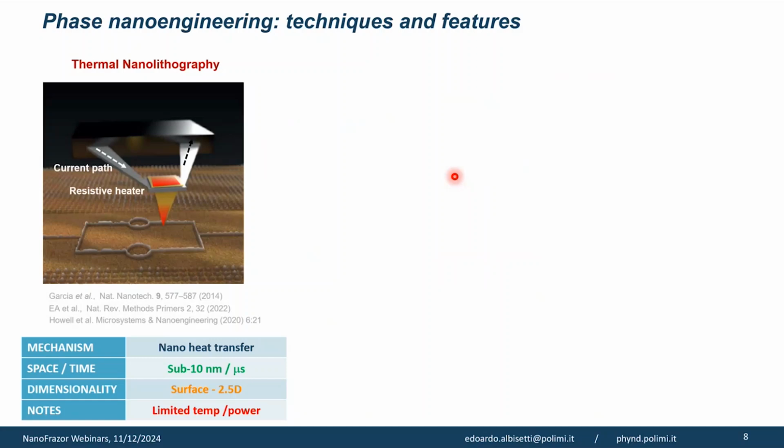different scenarios. And the important thing is that for producing this energetic landscape, we need somehow to transform the material. A very clean way to do it is to deliver energy to the material in a highly localized way. And of course, the first technique that we used for doing this was thermal nanolithography, because it's really good for that, because it's clean. You don't really change the atoms within the material. You change maybe the disposition of the atoms, so you change the phase, or you can trigger reactions at the nanoscale, being really precise in the temperature.